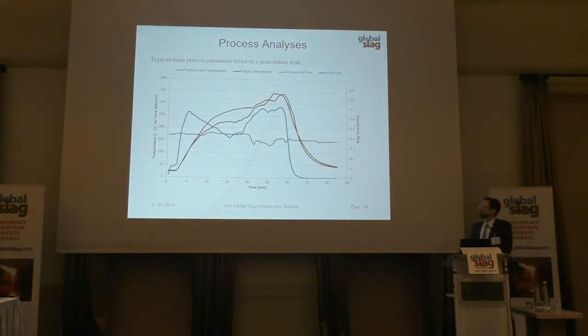Here is an overview of the main process parameters of a typical trial, what we are doing with this plant. We are starting at cold condition. That means the granulate bed is in cold condition and has to heat up. The gray line is the process airflow. We have a process airflow of about 150,000 to 170,000 standard cubic meters per hour through the plant. The blue line is the slag flow, which we calculated in the process. You can see we go from 0.4 up to 0.7 tons per minute into the granulator.